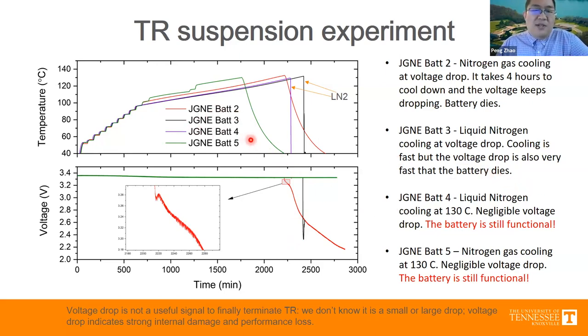So that means maybe the voltage drop is not a good signal. As soon as you observe a voltage drop, there is already strong damage inside of the cell. Now for batteries four and five, we apply cooling when the temperature is around 130 degrees Celsius. Say in the purple line, as soon as the temperature reaches 130, we apply liquid nitrogen cooling, which immediately cools down the cell. At the same time, the voltage remains. And we say, maybe at this point, we don't need liquid nitrogen cooling. So we just use nitrogen gas cooling for battery number five when it reaches 130 degrees Celsius. As you can see, after very slow cooling, the voltage still remains.